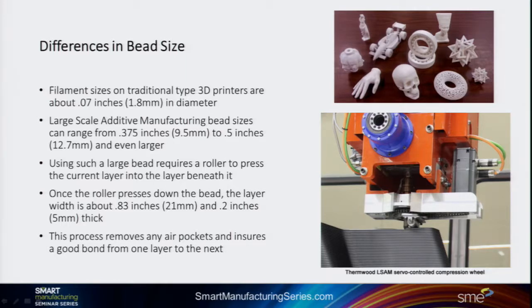So once that wheel applies pressure to the bead that's being laid down, it's going to compress that out to about 0.83 inches wide from that 1/2 inch bead and about 0.2 inches thick. That's also going to help ensure that there are no air bubbles between the two layers, giving you good layer-to-layer adhesion and virtually zero porosity throughout that process.